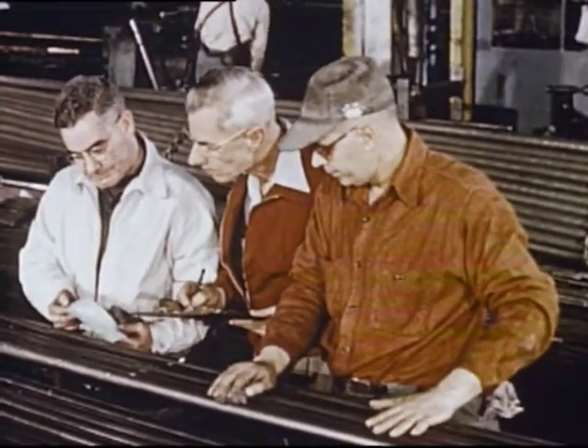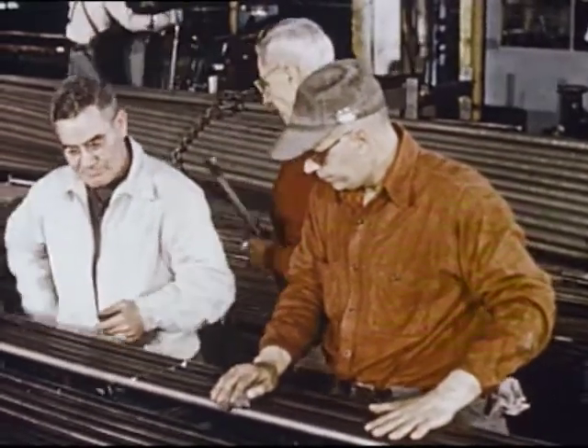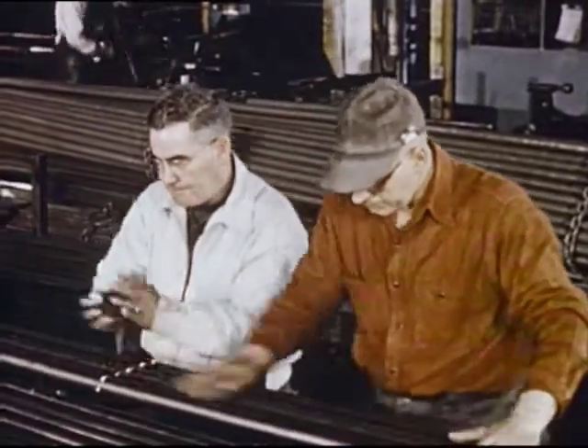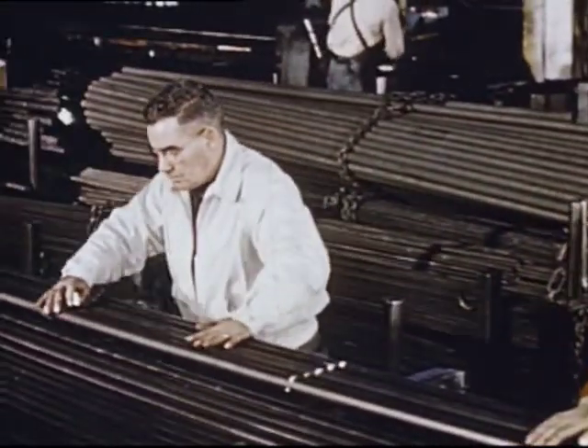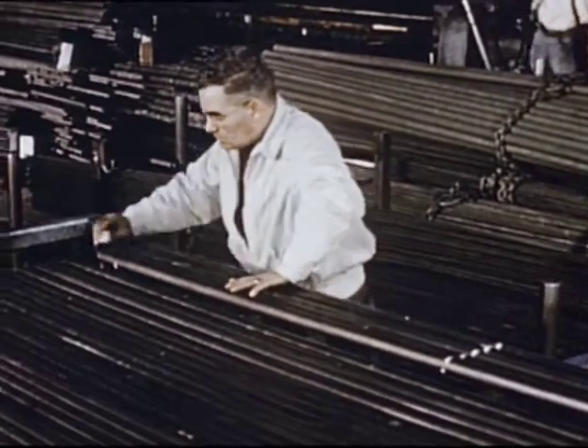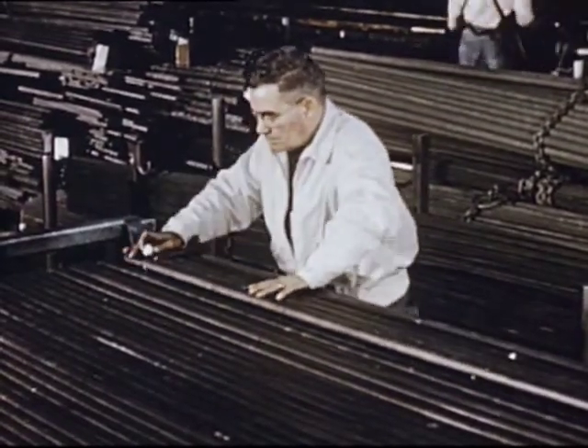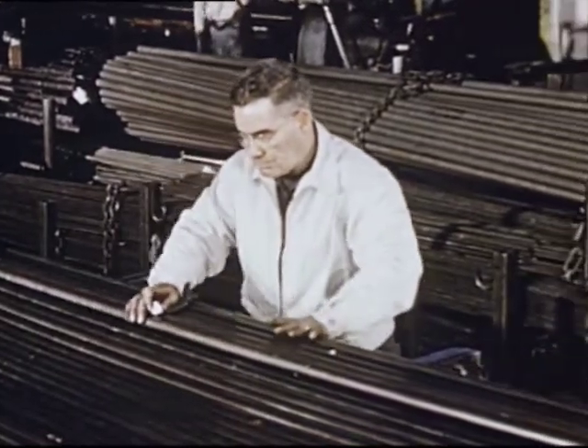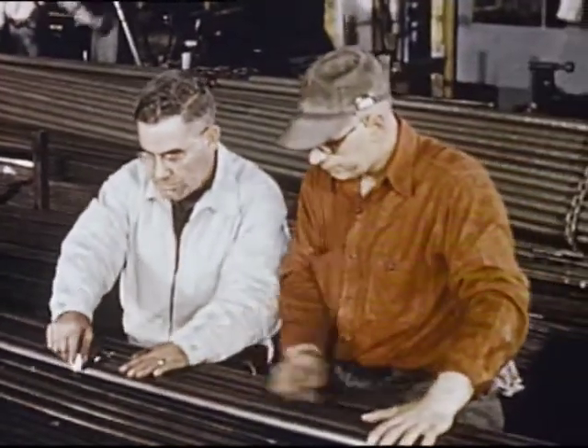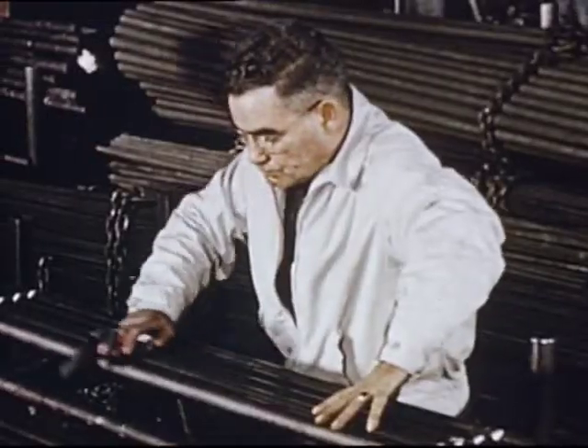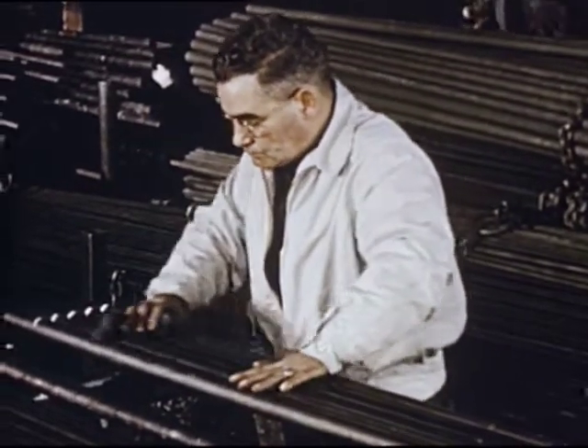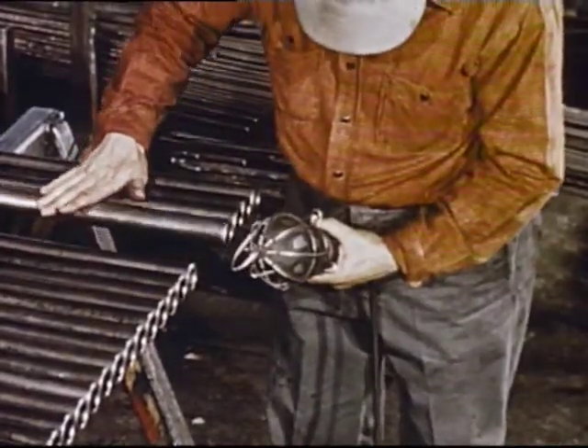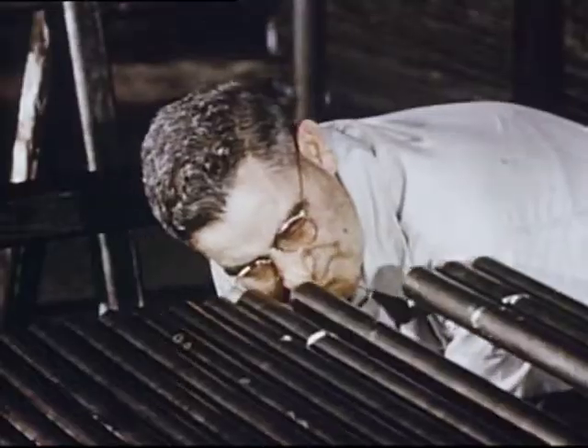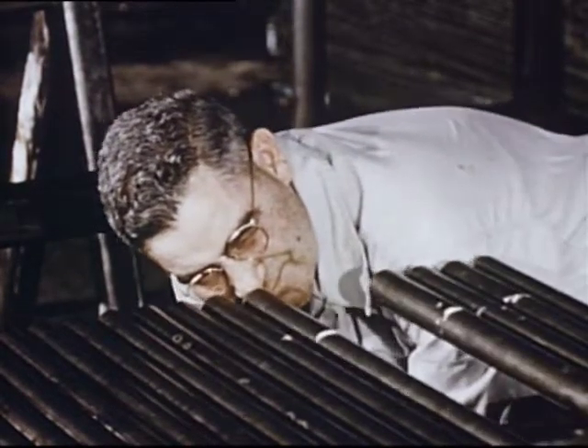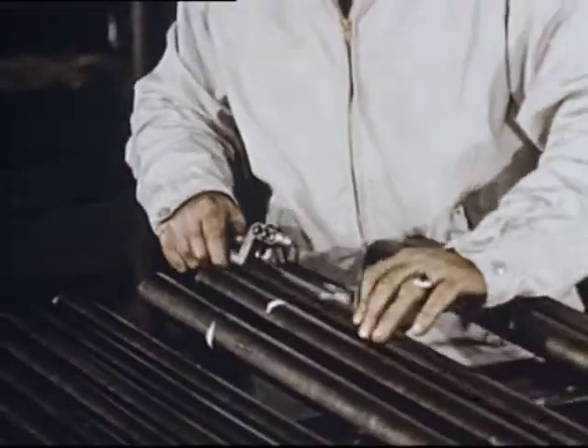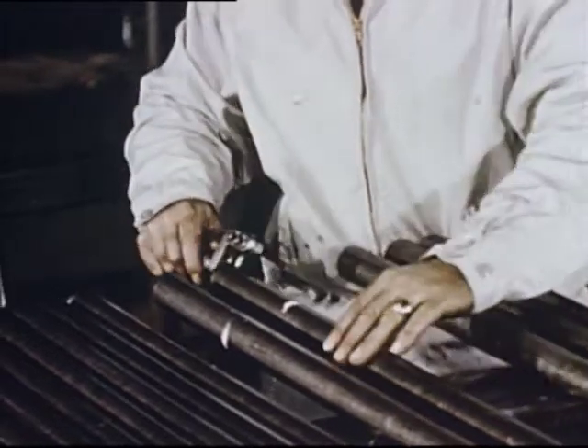Throughout the entire process of converting solid steel billet into cold-drawn seamless tubing, repeated checks and inspections have been made to detect any flaws or signs of failure. Regardless of this fact, a series of final inspections is still made to make sure every tube meets the original specifications. The outside surface of each tube is carefully checked, as is the inside surface, to make sure the tubes meet specifications and customers' requirements. The uniformity of wall thickness is checked with micrometers and snap gauges.